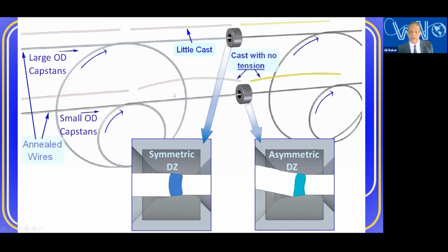Now, going into the same die where you have your cast, you have your bowing. That means even though the wire is straight going into the die, there are asymmetric residual stresses, and they cause a different deformation zone. The deformation zone is asymmetric. Again, there's compression here. It takes longer for the material here to yield, and the wire decides for itself, I'm going to shift to a more favorable position. And so that comes out also with a bow. As I mentioned before, asymmetric drawing begets asymmetric wires.